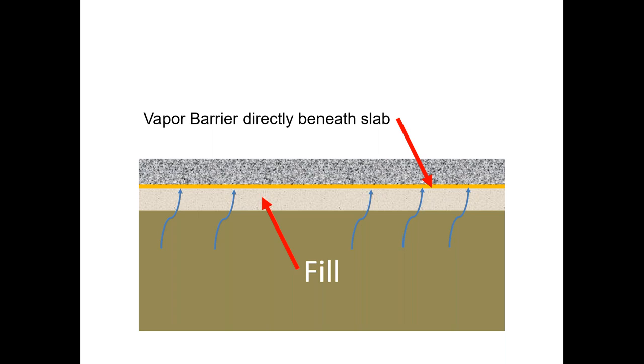I've seen studies that say that actually having the vapor barrier, and I've talked to some very knowledgeable engineers like Scott Tarr and Peter Craig on this, who deal in this every day. They'll tell you that having the vapor barrier directly beneath the slab actually results in less curling than having it below the sand layer. Keep in mind that it's differential cure that causes our problems in our slabs. So if it's curing differently on the bottom than it is on the top, we can have curling or warping of the slab. And curling goes both ways. The slab doesn't necessarily have to be drying more on the top than on the bottom for it to curl. It can be drying more on the bottom than on the top for it to curl. So if you were to talk to someone like Scott Tarr, what he would tell you is that the moisture can only go up through the concrete.